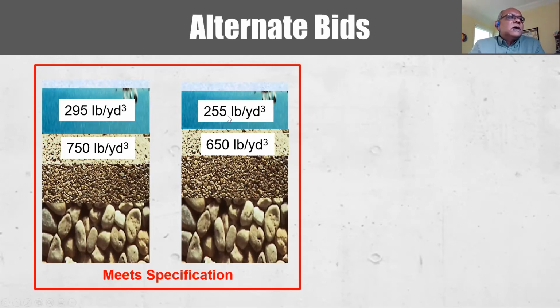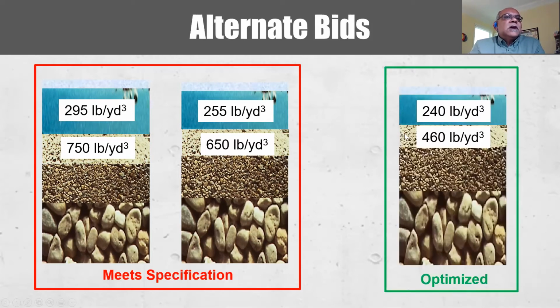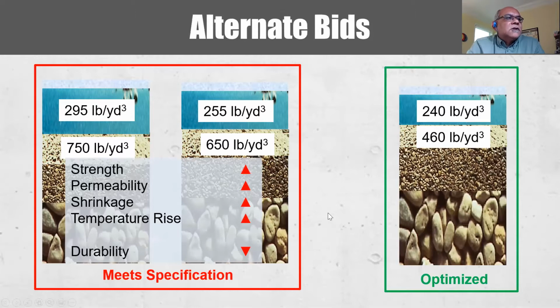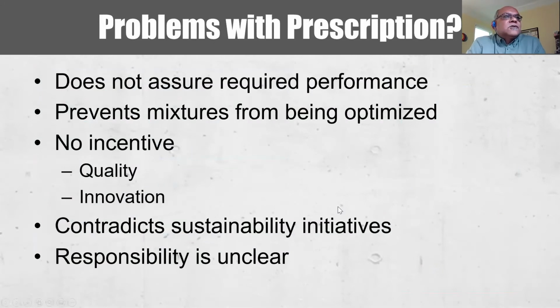However, if those prescriptive requirements were not in place, what we could get is a much better optimized mix that will give you the required performance, that will not generate too much heat, will have a reduced potential for cracking, and achieve the required design strength for that purpose. As you can see, the two options on the left that are controlled by the prescriptive requirements will have a very high strength, significantly over-designed, and will have a reduced durability. And so that's some of the issues regarding prescription: it doesn't necessarily assure that you get a required performance, or it might have some unintended consequences, such as increased potential for cracking, etc.